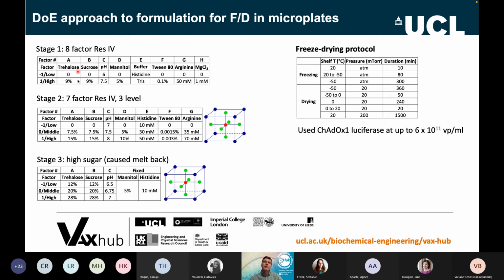We started off with a simple 2-level factorial screen of a number of different excipients, much of which you will have seen in that Chen formulation I showed you earlier, spanning the concentration range used there. Having done that work, we then went into more detail with a 3-level approach, and then we looked at this higher sugar one that didn't work. We had a fairly standard freeze drying protocol, and the platform was ChAdOx1 with a luciferase gene, which facilitates the infectivity assay, at 6 × 10^11 virus particles per mL as our loading.